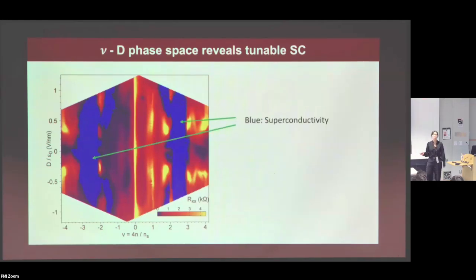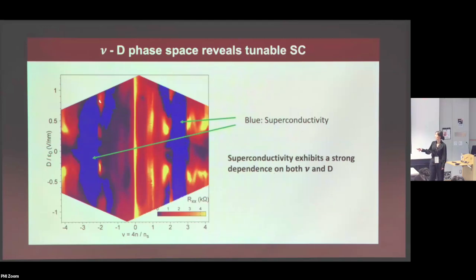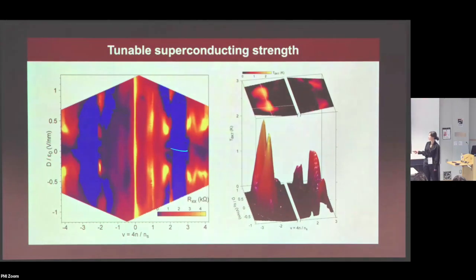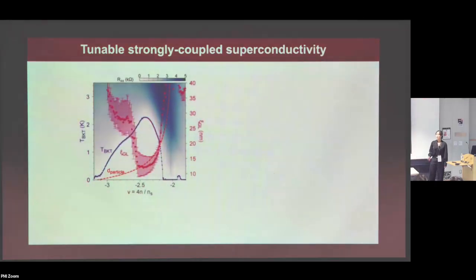So there are so many things going on, but I just want you to focus on these blue regions of zero resistance, which is the superconducting region. And you can already see that the region where superconductivity appears is very tunable within both the displacement field and the filling factor in the system. And it's not just the extent of the superconducting dome, we can also measure the TC of the entire phase space, and this is the map of the TC. You can see that the actual TC is also controllable as a function of displacement field and charge carrier density.